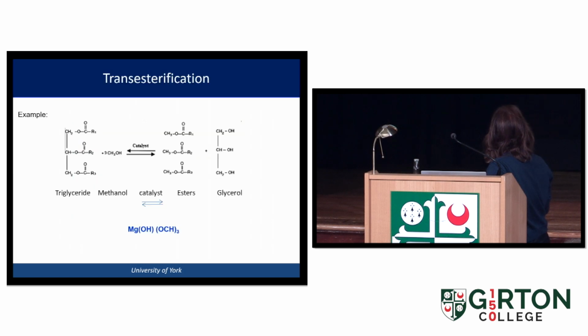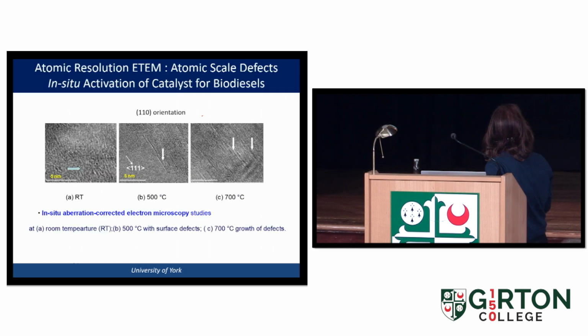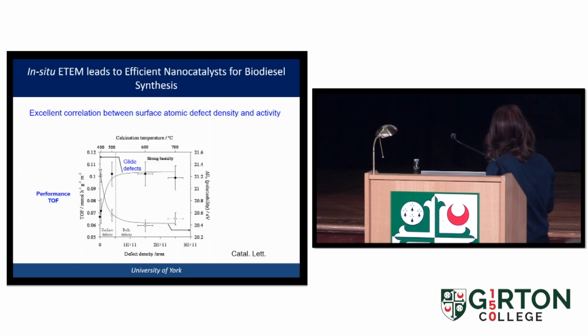What we do is convert that in the presence of alcohol into fuel, and we get a little bit of glycerol. But glycerol is used as a sweetener in cakes and things that you buy in your supermarket, so it's not wasted. When we actually do the reaction in our environmental machine, we see these atomic scale defects, structural modifications. We didn't know they existed, and without the machine, we couldn't see them. When we correlate them with the performance, you can see in the presence of these defects, the performance is maximum. By operating in this regime, we have been able to develop efficient nanocatalysts for biodiesel synthesis. We are now expanding that work to grass.